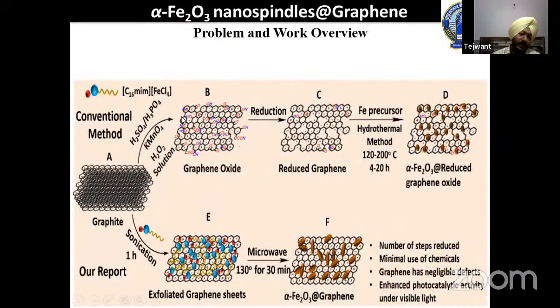Another interesting one I'll show you is the preparation of iron oxide nanoparticles at the surface of graphene in a very simple way, which have been used again as the photocatalyst. What happens in the conventional way? The conventional method is Hummers' method for the exfoliation of graphene. In Hummers' method, we have to use sulfuric acid, phosphoric acid, KMnO4, and other toxic materials such as hydrogen peroxide for the exfoliation of graphene, which generally comes out in the form of graphene oxide. In the next step, we reduce graphene oxide to reduced graphene oxide. In that case, we have to add the iron precursor by a hydrothermal treatment method at a very high temperature for a longer time. We can find the alpha-Fe2O3 nanoparticles present at the surface of reduced graphene oxide. So we can see so many chemicals, a large number of steps, and high temperature.